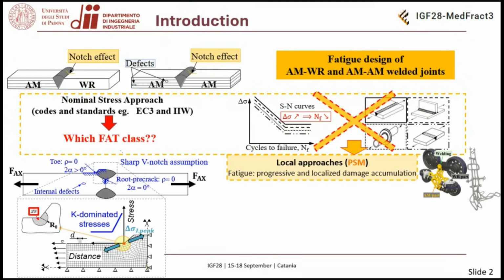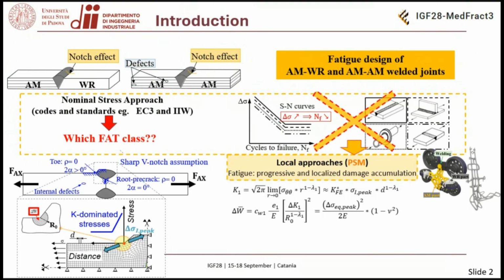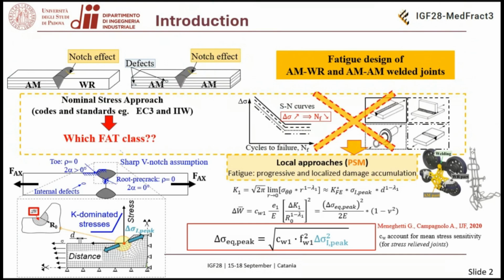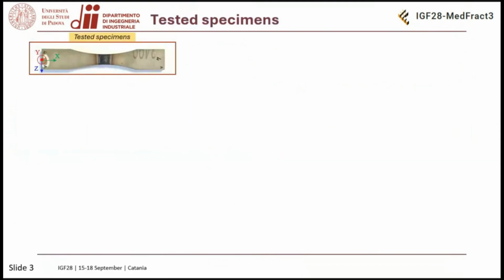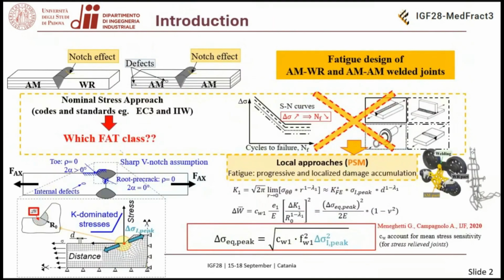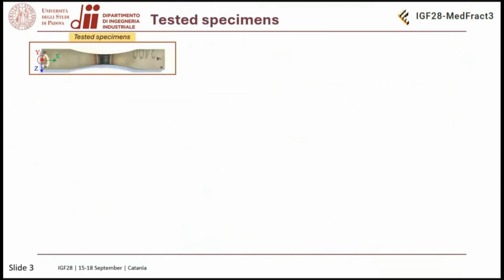In this way, with a finite element analysis with a coarse mesh, we can estimate the NSIF at the weld toe, and then by assuming the mean strain energy density as a failure criterion, we can rewrite this expression in terms of an equivalent peak stress, and so we can use this equivalent peak stress to estimate the fatigue strength of our joints.